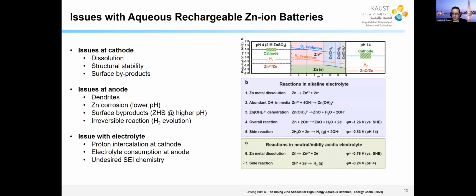Somebody summarized these actually in this paper very nicely here. They have the Pourbaix diagram, and they have the set of reactions, the side reactions that happen in alkaline electrolyte and in neutral or mildly acidic electrolyte. So obviously you see that we prefer to work in mildly acidic electrolyte because the number of side reactions, at least in principle, is lower.